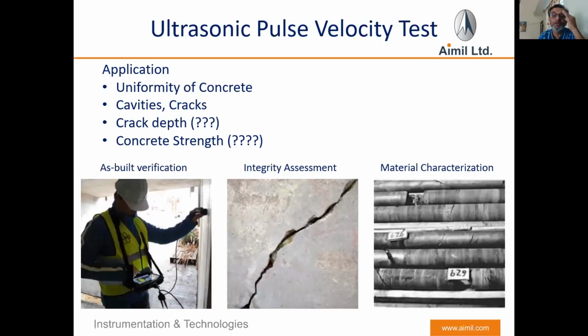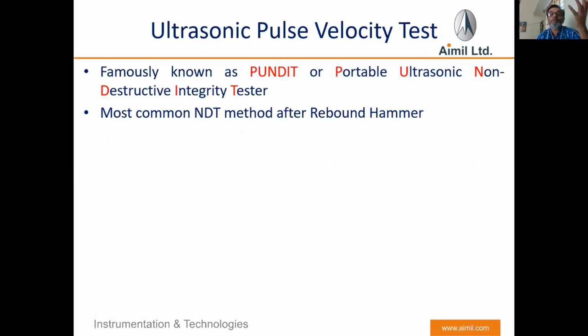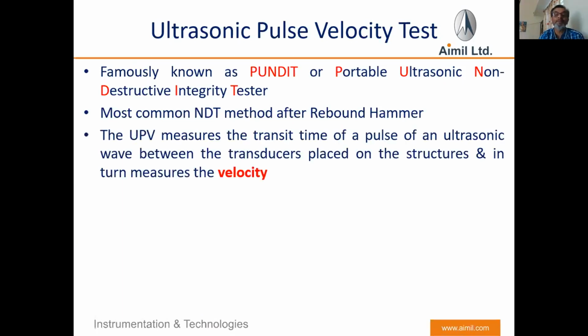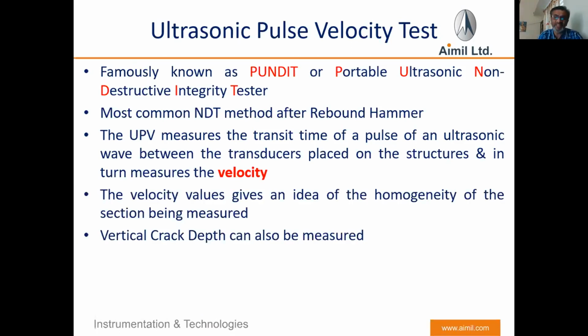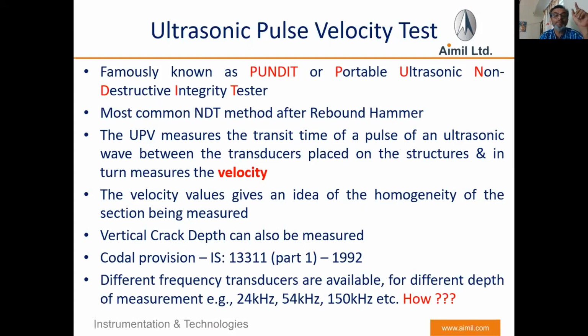So these are the applications. As build verification, you can do the integrity assessment of any concrete structure, or material characterization can also be done with ultrasonic pulse velocity measurement. It is famously known as PUNDIT, the abbreviation for portable ultrasonic non-destructive integrity tester, and it is the most common NDT method after the rebound hammer. As I said, it gives the time, and ultimately you measure the velocity. The velocity value gives the idea about the homogeneity of the section being measured, and vertical crack depth can also be measured. There is a codal provision, IS 13311 part 1, 1992, and different frequency transducers are available for different measurement depths.